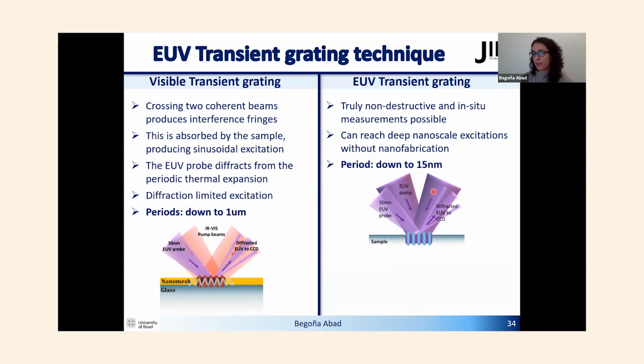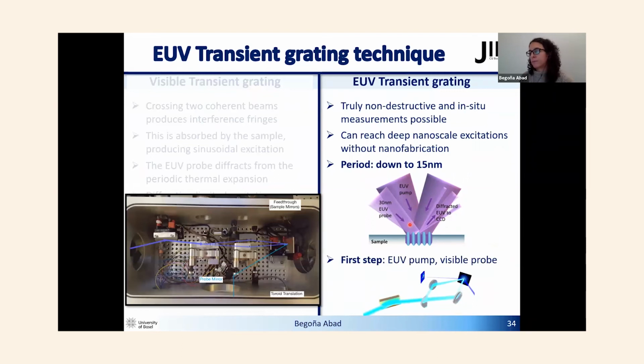However, this is extremely challenging because working with this type of light requires using vacuum, because this light gets absorbed within a micron since it's created. Also, refractive optics don't work for this type of light, so we need to use special optics, and the flux is also an issue, since you lose a lot of flux when using this reflective optics. It's engineering-wise really challenging. So we started by doing EUV pump and visible probe, and as you can see here, this is how the system looks.